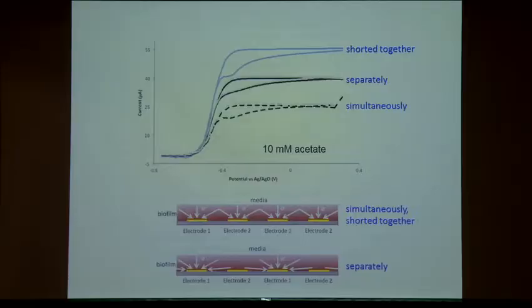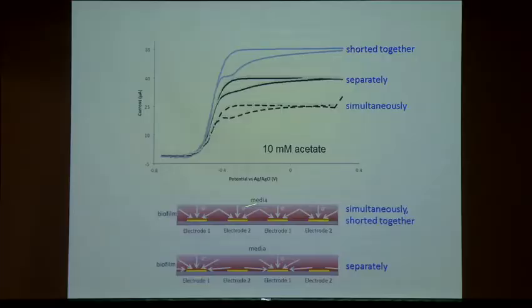But the point is that this last step, getting the electrons between the biofilm and the electrode surface, appears not to be the limiting step when I'm growing the biofilm, because I can actually pull more current through this interface when I do the electrodes one at a time. The fact that I'm getting more current here is also very indicative of a diffusive process. Here the electrodes are sort of competing against each other. So if I'm a microbe over here, I might be able to throw my electron this way or this way. Here now it's no longer competing, and this electrode is gathering more electrons from, say, a larger volume of the biofilm.